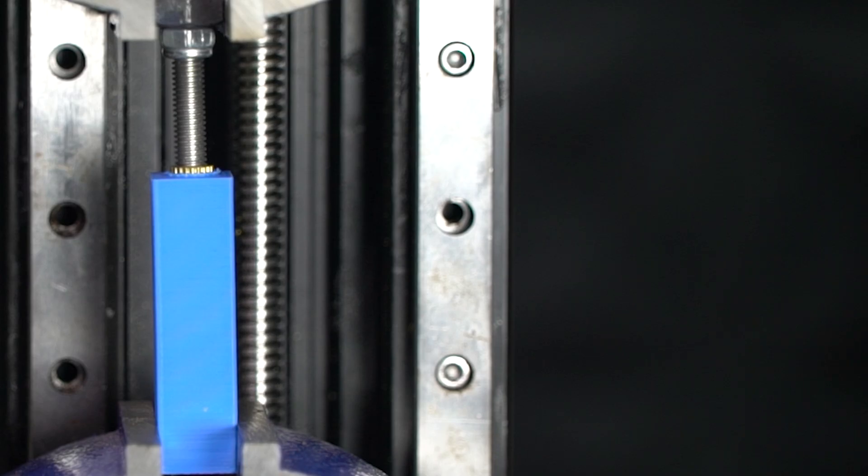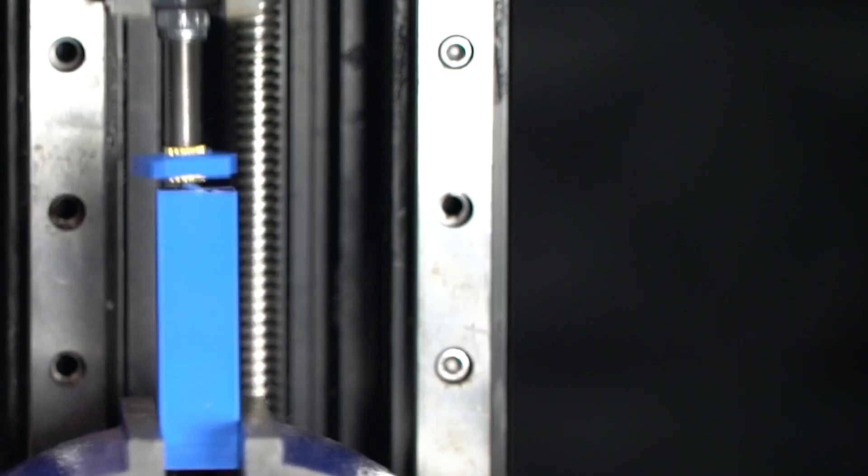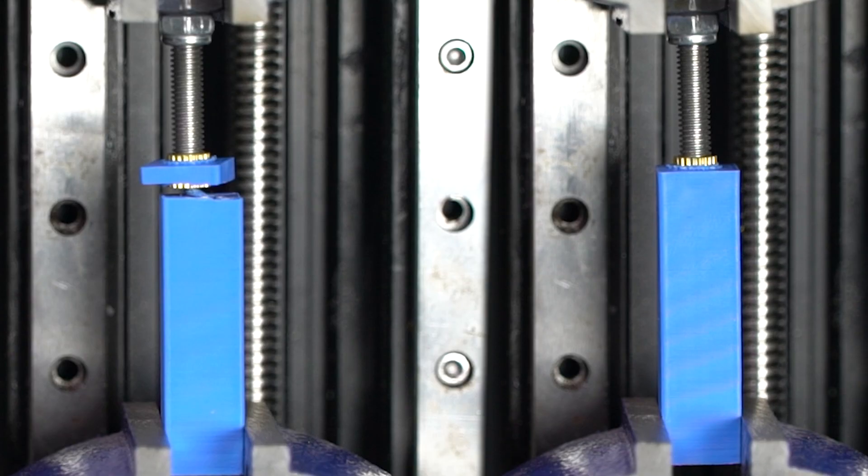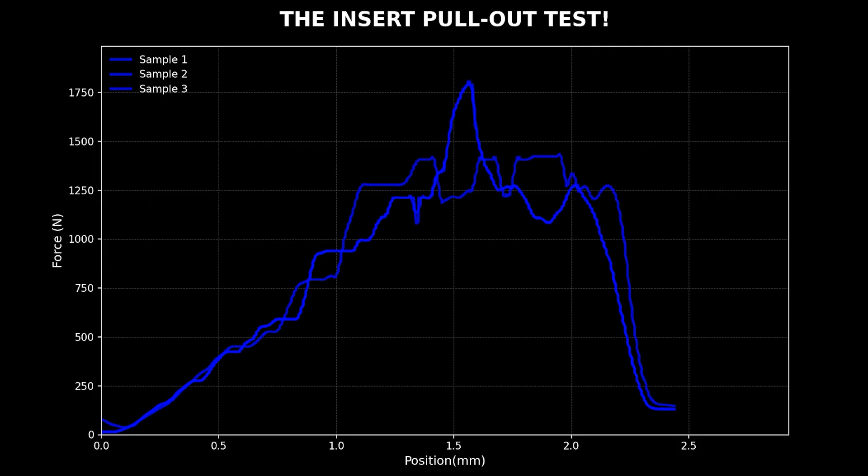And finally, PLA, the crowd favorite. Wow. Look at that. The insert didn't pull out. It literally cracked the layer. Unexpected results here. A massive 1,805 Newtons. Incredible power.